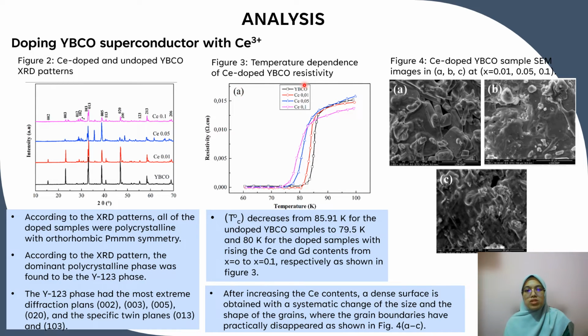Figure 3 shows the temperature dependence of Ce-doped YBCO resistivity. The critical transition temperature decreased from 85.91 K for the undoped YBCO sample to 79.5 K and 80 K for the doped samples, with the rising Ce and Gd contents from x equal to 0 to x equal to 0.1 respectively, as shown in